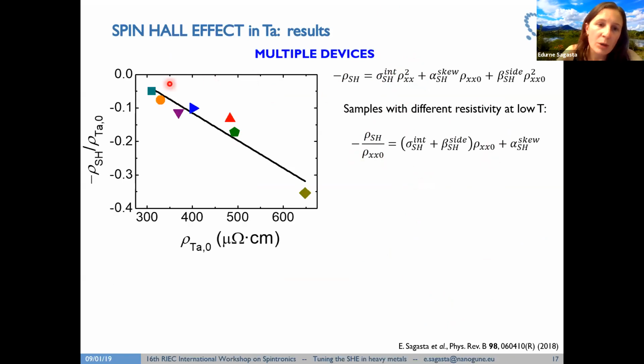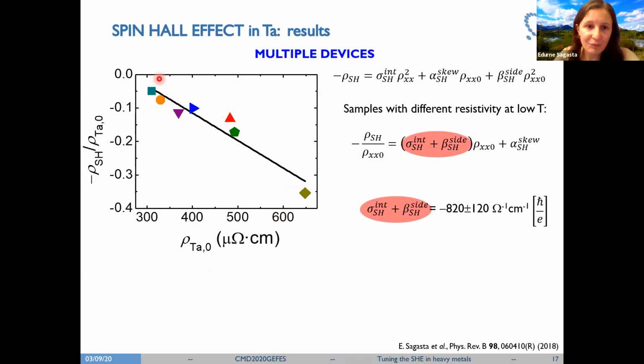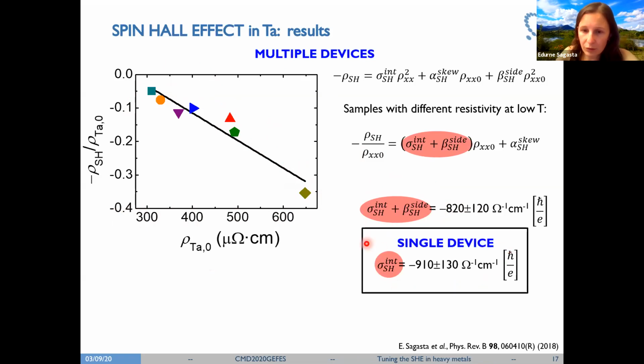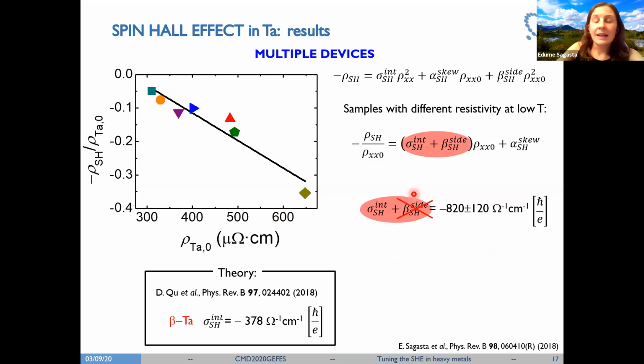So here we see the results that we obtain for the 7 devices, 7 lateral spin valves that we fabricated made of tantalum, where we can see now that the resistivity varies much more. So from the fitting, we can extract now the slope, which will give us the intrinsic plus the side jump contribution. And if we compare the value with the value that we obtain for the single device, we see that they are compatible. So this led us to say that the side jump contribution is negligible in the case of tantalum. And if we compare with the theoretical results, we can see that the theoretical results show a much smaller value. In the case of the skew scattering angle, we see that it is positive and quite a large value.